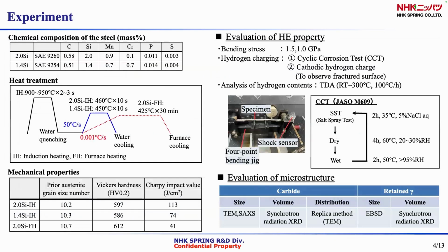Now I explain the experimental method. Two types of spring steels with different silicon content were used. Heat treatment is shown here. In order to eliminate the grain size differences, induction heating (IH) was used for quenching, and IH and furnace heating (FH) were used for tempering. The specimens were three types of steels with different silicon content and tempering speed.